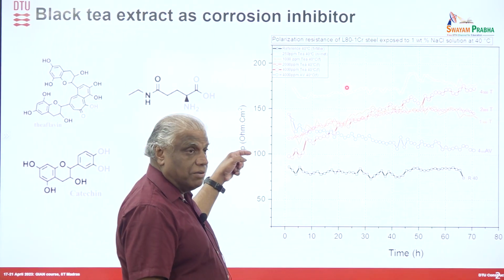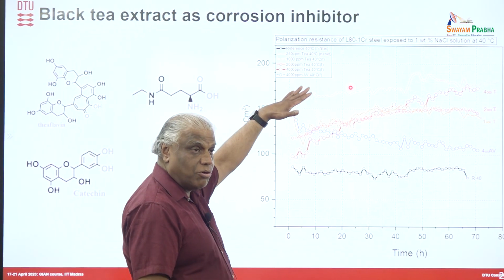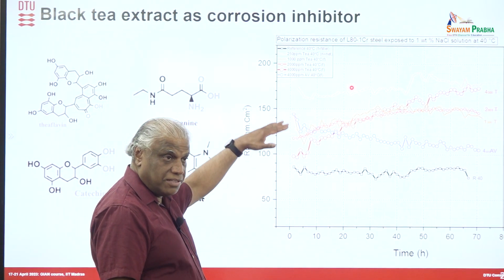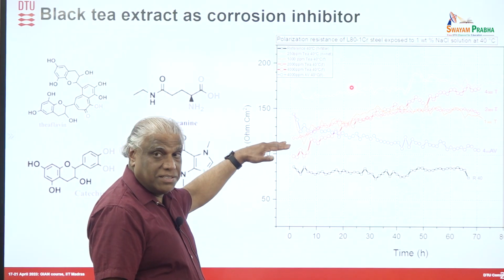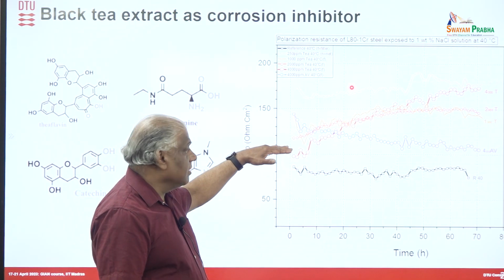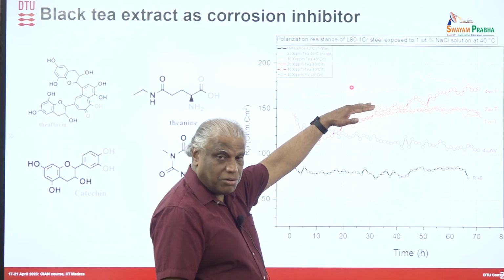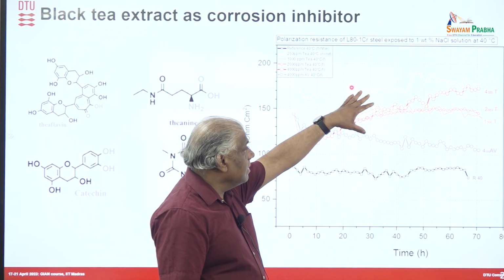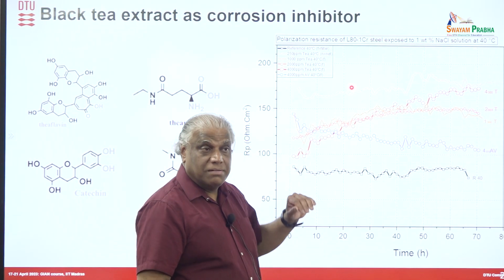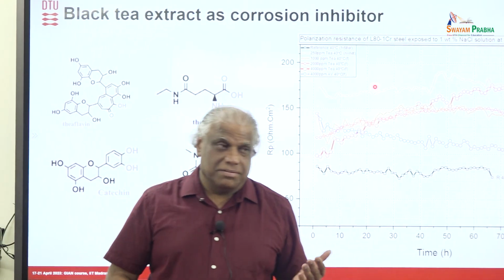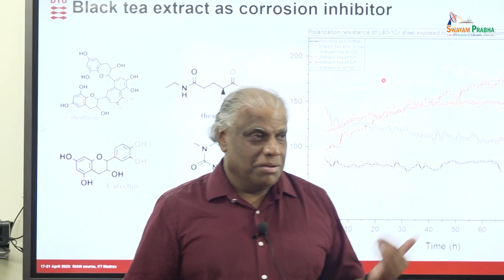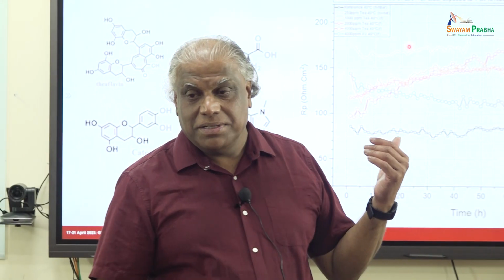This is the Rp value, the polarization resistance from the linear polarization curve. So if the Rp value increases, corrosion is decreasing. You can see that again this is giving a good inhibition. Is it as good as this imidazoline? No. Probably it gives 60 to 70% inhibition.